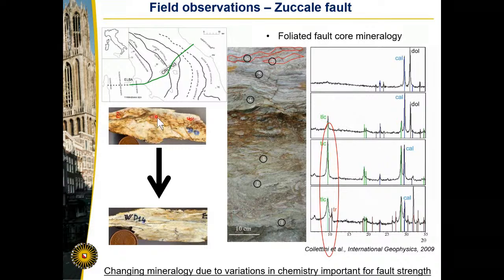And as we go from the host rock into our fault zone, which has accommodated kilometers of displacement, we can see that we start to see this foliation, and we start to see in the XRD more and more talc appearing. So the talc is allowing this fault to slide under a low shear stress. So without the formation of this talc, this would not be possible.